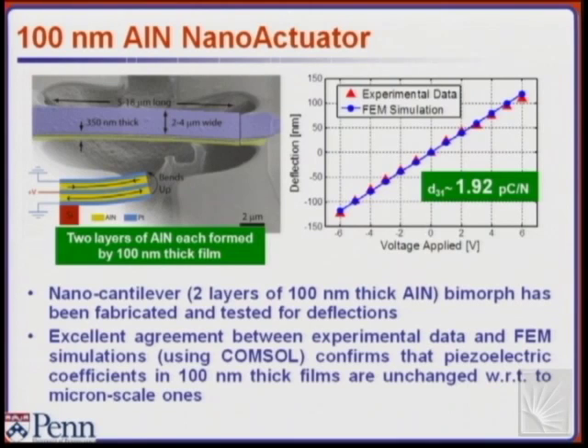So it's a 350 nanometer total thickness, and we varied the beam length between 5 and 18 microns, and for all of them we got a pretty consistent curve that matches the FEM simulation for a given bulk-like piezoelectric material. So we're getting a d31, which is the effective coefficient that we use for the transduction, that is actually comparable to the microscale films. So very promising for miniaturizing this device.